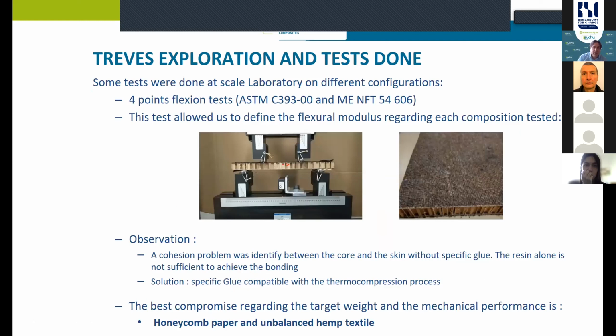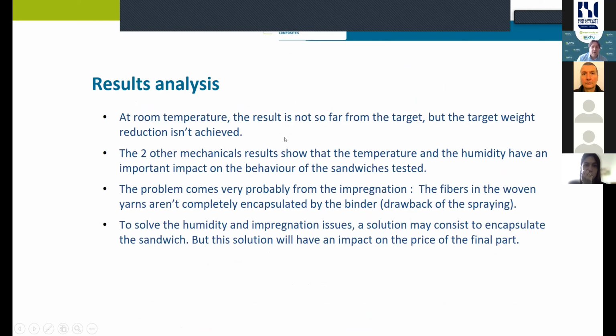So we have done many various testing and mechanical verification of the properties. We confirmed some things that were proven in the past, that we definitely need a specific gluing of the skins onto the honeycomb. So it's a confirmation of things that were known before. We had difficulties, as explained just afterward, to impregnate our materials. The problem of a woven fabric is that it was rather heavy. We had 350 grams per square meter. And then with a simple spraying technique, there is a problem. The compression in the mold was not solving the impregnation issue. So the weight is slightly too high.